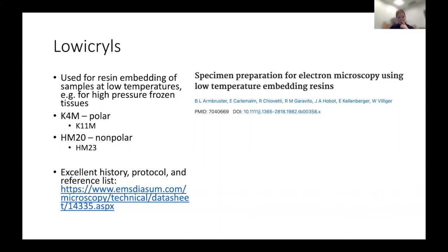So the original ones were K4M and HM20, polar and non-polar resins. And then there were a couple of improvements, K11M and HM23, and these resins work just like the others, polar and non-polar, but they work at even lower temperatures. So I don't have a lot of experience with this, but I find them quite interesting. And if I were going to get into high pressure freezing without the desire to bring samples back up to room temperature, I would use them. When I've done high pressure freezing in the past, I have done freeze substitution so that I could do further staining at room temperature.